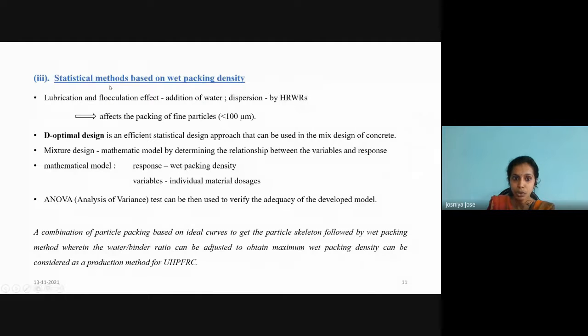So statistical methods were also developed, and these were based on the wet packing density. Why wet packing density? Because on addition of water to the mixture, lubrication and flocculation effects can take place. And high range water reducers can cause dispersion, and this can significantly influence the packing density of the matrix, especially in cases where the particles are finer than 100 micrometers. So a statistical method, the D-optimal design approach, is used for the mix design of concrete. This method involves a mathematical model where the response is predicted by a number of variables. The response is the wet packing density, and the variables are the individual material dosages. And the adequacy of this model is tested using the analysis of variance test.